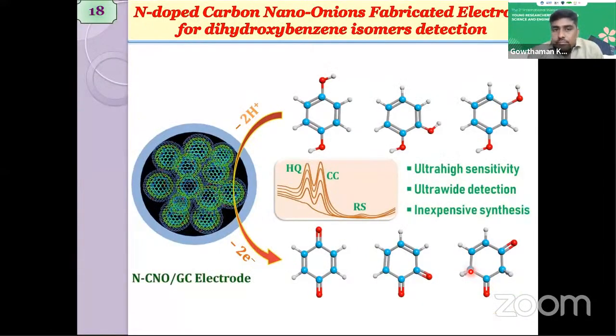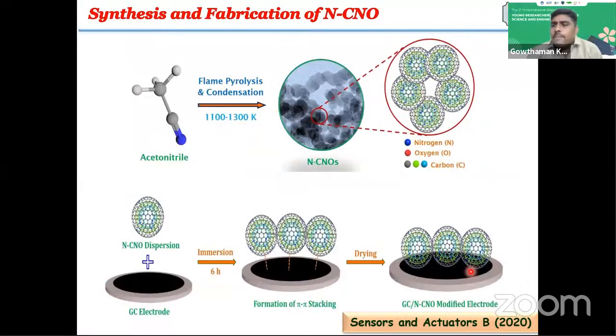So then carbon nano onions. Nitrogen doped carbon nano onions fabricated electrode for the simultaneous determination of dihydroxybenzene isomers like hydroquinone, catechol, and resorcinol. A very simple procedure was employed for the synthesis of nitrogen doped carbon nano onions. We take only acetonitrile in a flame pyrolysis method at 1100 to 1300 Kelvin, followed by condensation, which leads to the formation of carbon nano onions.